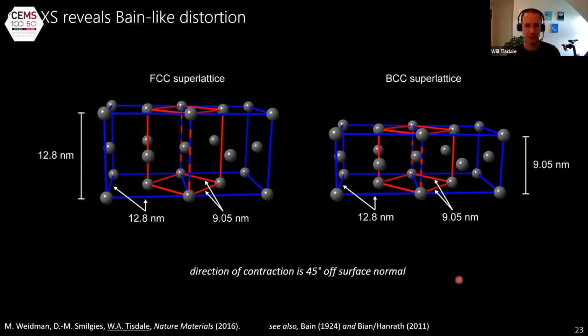The really interesting thing here, I think, is that the direction of this contraction is not in the surface normal direction. It's 45 degrees off surface normal. So this is not driven by a surface normal gradient in the solvent density. This is a coordinated transformation of the entire lattice.